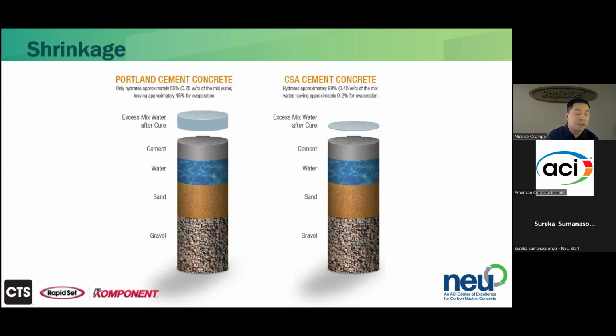A 0.25 water cement ratio is really required to hydrate the Portland cement, and the remainder is there for workability. If it's not bound, then it's available to evaporate and eventually cause shrinkage. In CSA cement, at a 0.45 water cement ratio, 99% of that water is going to be used to fully hydrate the material - hydrate CSA and hydrate belite.